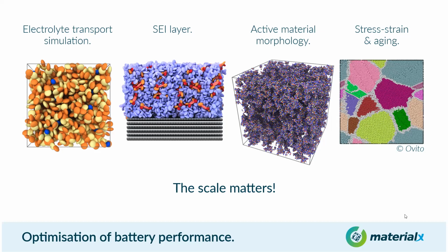Then an example of an active material morphology. So this sample in particular is 60 nanometers cube. And we can have a fractal geometry and explore complex shapes. Another important effect is that these materials undergo significant stress upon charging and discharging. So we can use the information simulated in the mesoscale to allow for ageing effects in these materials. So stress and ageing related to these cycles of compression and deformation of the materials.